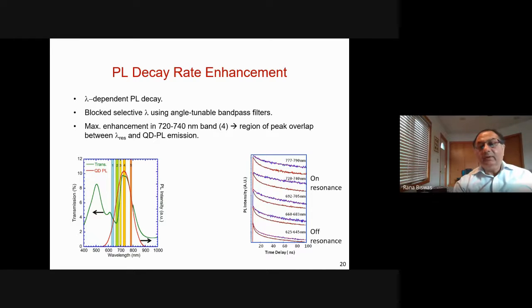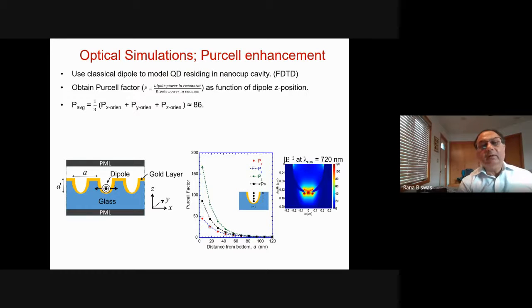So we established this very well experimentally, and then we simulated this effect by using finite difference time domain simulations by placing a classical dipole to model the quantum dot, and the dipole emits in X, Y, and Z polarizations, and the dipole can be placed at different positions within the nanocup. So it's typical in this field to obtain the Purcell factor, which is the ratio of the dipole power within the resonator to the dipole power in vacuum. So this is telling you how much the field is enhanced inside this nanocup, and how that is affecting the radiation power of the dipole.